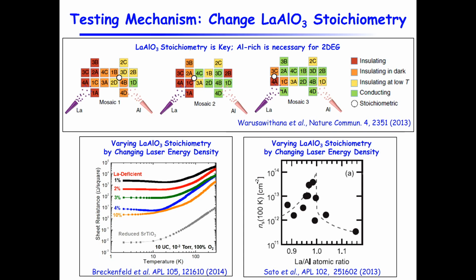There have been works that are trying to change the stoichiometry of lanthanum aluminate. This is the work from Darrell Schlom's lab using oxide MBE. They could put many substrates there, so that you can grow the materials with different stoichiometry. And the green ones are the conducting samples, and the red ones are insulating samples. From this, what they have seen is that stoichiometry is important. Right? All these films are grown under the same nominal growth condition, except that the composition is different. And you can see that aluminum rich is important for having this conducting layer. That's what that paper concludes.